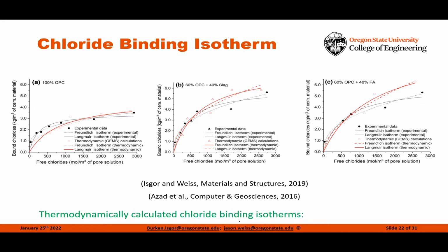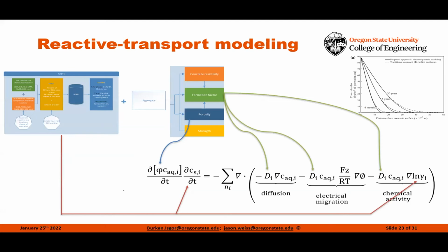So all of a sudden now we have the ability to take this approach and start to build it into a completely reactive transport model where we can capture the formation factor, the pore network, the porosity of the system, and the chloride binding, and predict things like the time to corrosion of a particular element simply by knowing the initial chemistry of the system. We can do the same types of predictions for things like freeze-thaw.